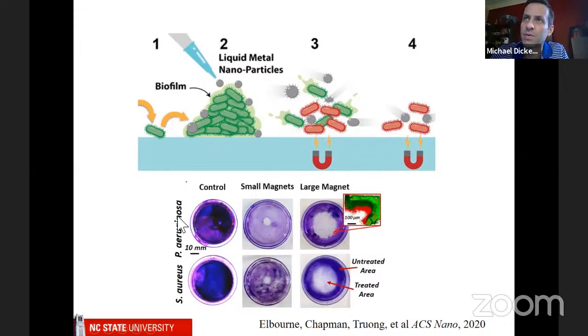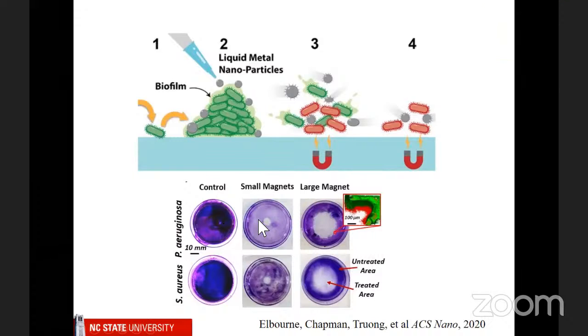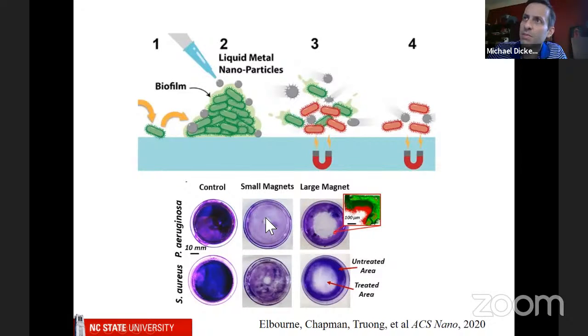So as an example, these funny names are two different types of bacteria that are very common. So if you grow them in a petri dish, this is looking top down, you'll see that they look purple, because they're stained purple, I believe. And if you use a small magnet, you can see that the bacteria in the middle of this dish gets killed. And if you use a larger magnet, it kills a bigger area. So basically, wherever we treat it with these gallium particles, it seems to be killing the bacteria. So I think it's a physical mechanism, but it's also known that gallium, well, Ga3+, is known to have antibacterial properties. So there could be multiple things that are happening here.